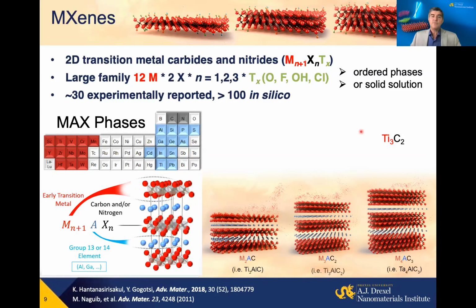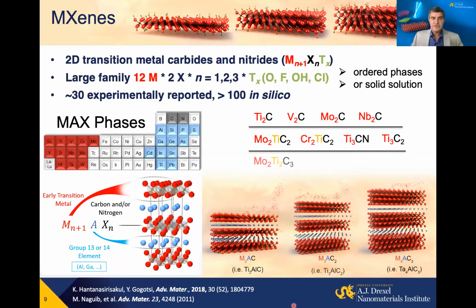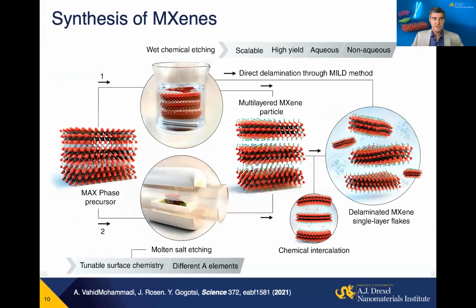And the first one and the most studied one is titanium carbide, Ti3C2. It's a very nice 2D material because titanium and carbon are both very common elements, abundant, inexpensive. And already in the first study by Michael Naguib, a dozen materials have been produced, also including solid solution on the X side, and I showed you many more existing today here. So the synthesis is done typically today either by wet chemical etching of MAX phase or other precursors, or by molten salt etching. So it's a chemical synthesis, which has its, of course, limitations,